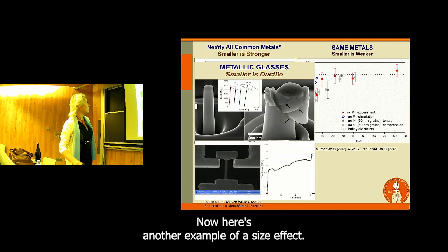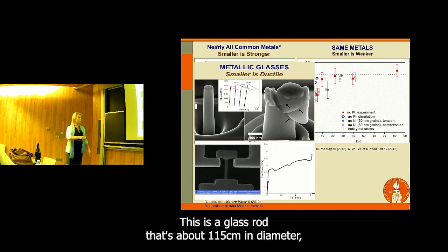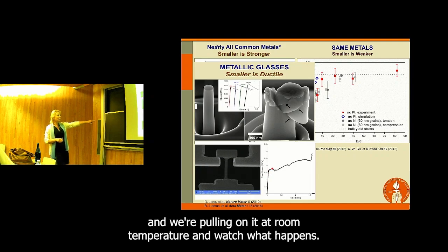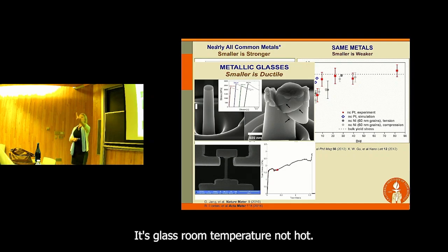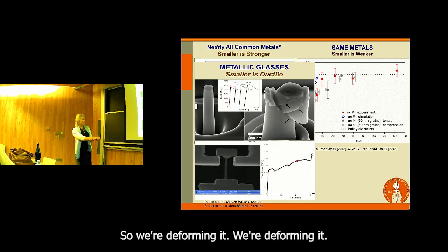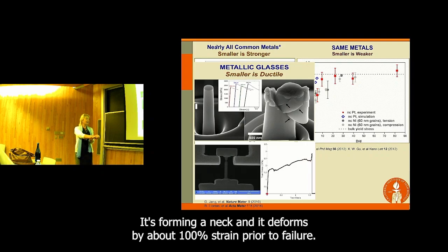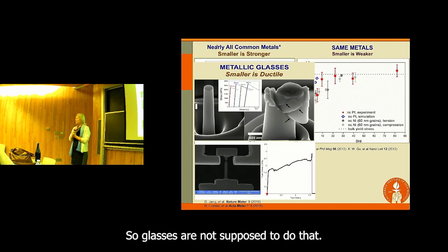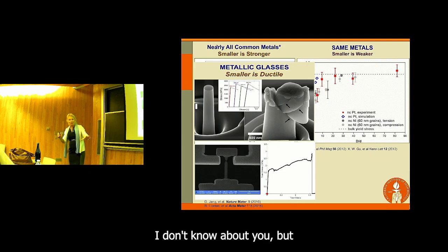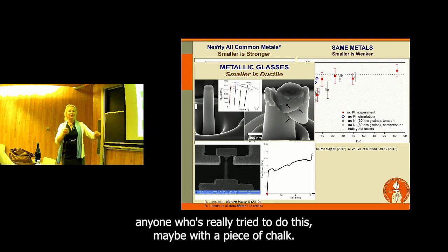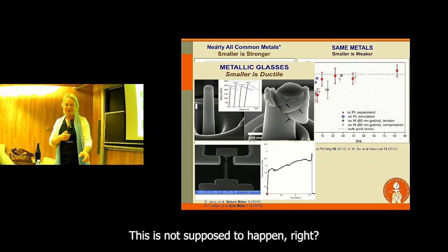Now, here's another example of a size effect. This is a glass rod that's about 150 nanometers in diameter. And we're pulling on it at room temperature. And watch what happens. It's glass, room temperature, not hot. So we're deforming it, it's forming a neck, and it deforms by about 100% strain prior to failure. So glasses are not supposed to do that. I don't know about you, but anyone who's really tried to do this, maybe with a piece of chalk, this is not supposed to happen, right?